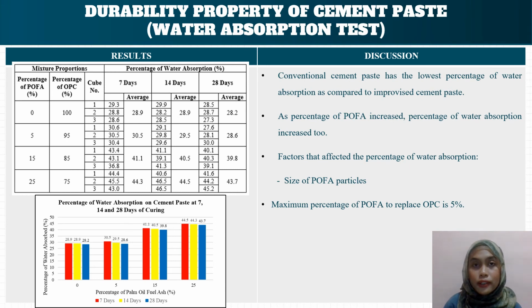Lastly, to analyze the durability property of cement paste, a water absorption test was performed. From the result shown in the slides, it can be seen that conventional cement paste has the least percentage of water absorption as compared to the other improvised cement paste. However, by comparing only among the improvised cement paste, the percentage of water absorption will be increased as the percentage of POFA added into the mixture increased.